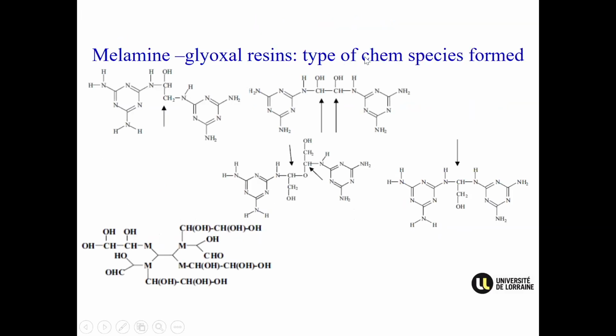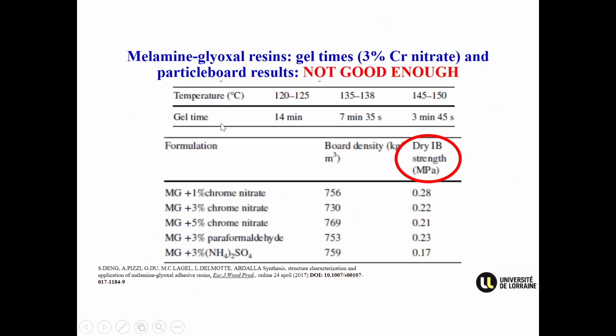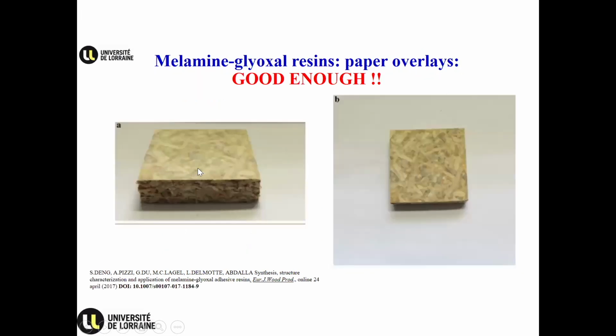Melamine glyoxal resin, the type of chemistry species formed. You can see the melamine glyoxal resin. They have a very big problem. With chrome nitrate or with paraformaldehyde or other things, the dry internal bond strength is not sufficient at all. It is very good instead for paper overlays, that is paper impregnated with melamine glyoxal resin, and it is good enough for paper impregnation, passed all the tests of the European standards.